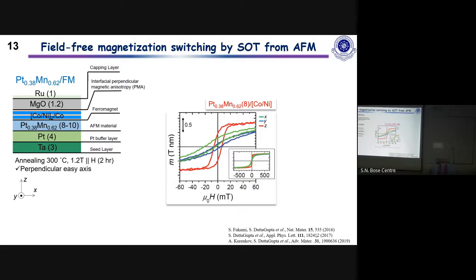How do you make the contacts there? With the top of the capping layer, you make the contact? Actually, what we do is that you first make your device, and then in the same ion milling which you are using to etch your sample, you can etch a bit more when you are doing the patterning for your contact pads. That will remove these layers, your metal will get exposed, and you can deposit the contact metal.